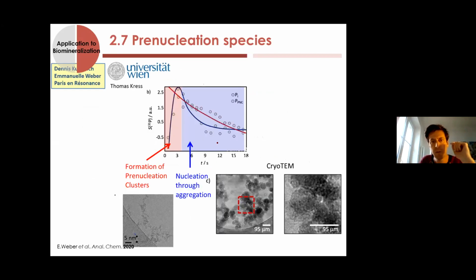So here, let's resume the results. When you track the signal, you can distinguish two phases: the rise of the signal of the prenucleation species, corresponding to their formation, and then the fall, corresponding to the aggregation.